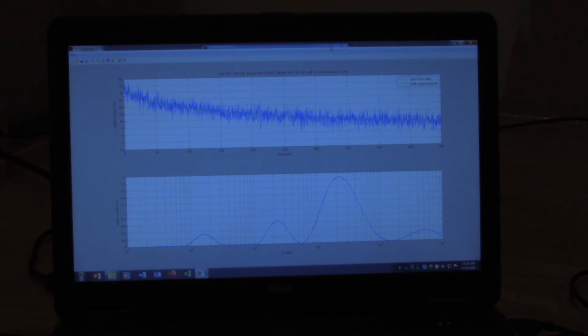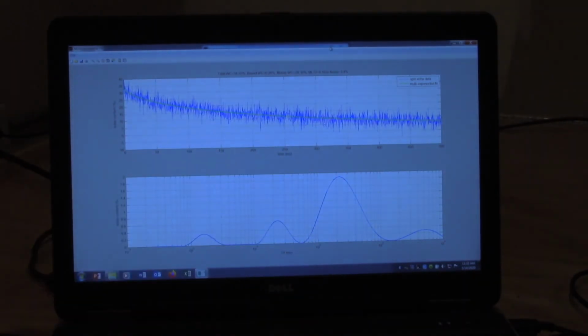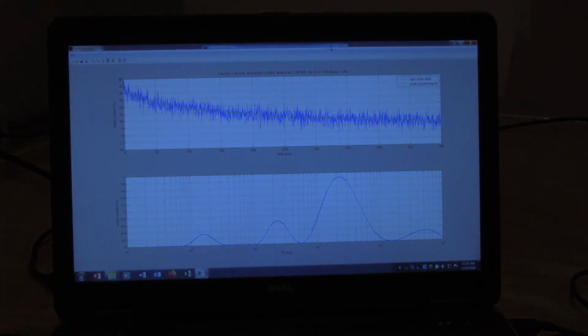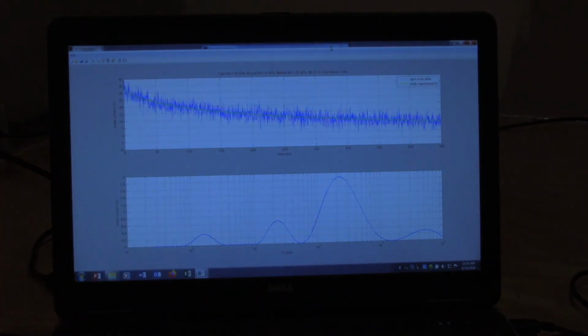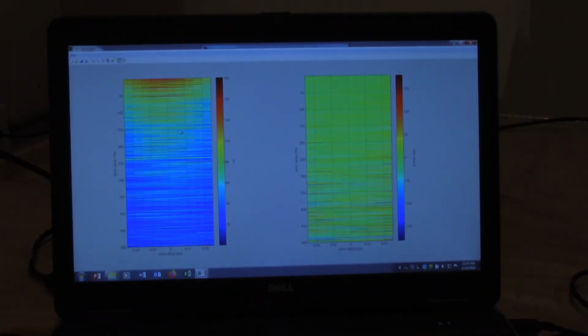The total water content is reported as 34.5%, and it is divided into bound and mobile as well. We get a T2 log mean time, which could be used for something like putting into an SDR equation for estimating permeability. And finally, with 20 stacks, we have a noise level of 3.4%.